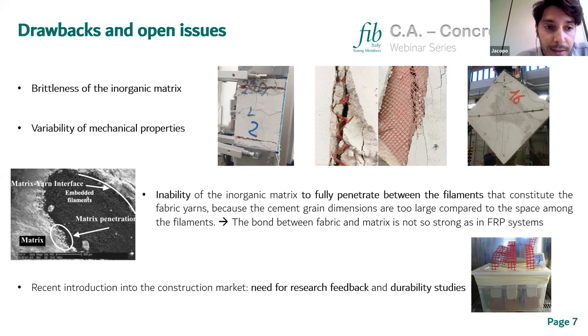The most important characteristic of this technology of the FRCM is the fact that the mortar is not able to fully penetrate within the single filaments of the reinforcement. This is because the particles of the mortar are too big to go through the filaments. And so this results in, let's say, not very good bond between the reinforcement and the matrix.